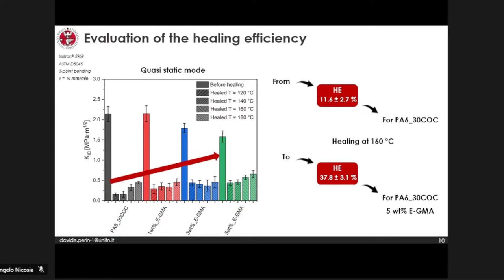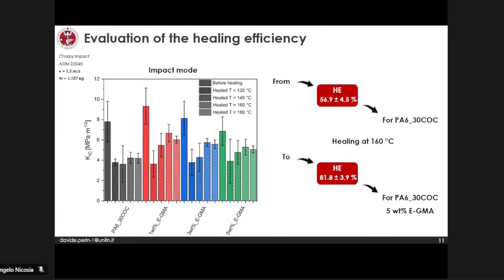But the situation changed dramatically in impact mode. By increasing the content of compatibilizer and by increasing the healing temperature, we were able to increase a lot the so-called healing efficiency. As a reference, for the process performed at 160 degrees C, we obtain, without the compatibilizer, a healing efficiency of nearly 57%, and with the compatibilizer, we obtain a healing efficiency of approximately 82%. That is remarkable for this polymer. But let's see why there is such a difference.